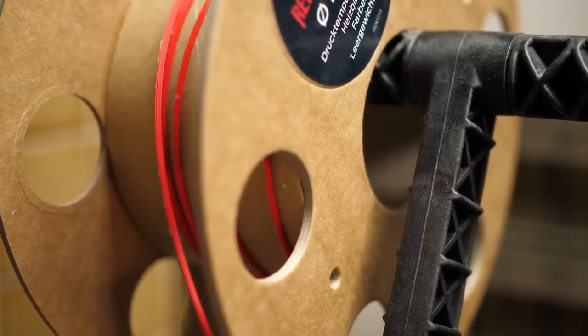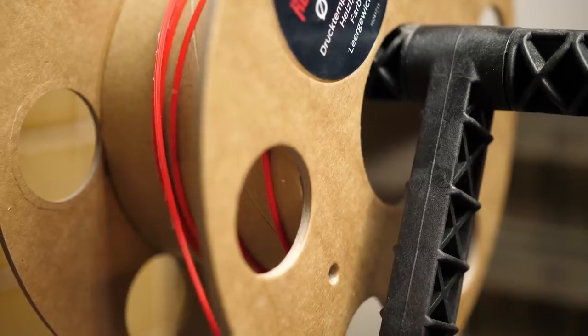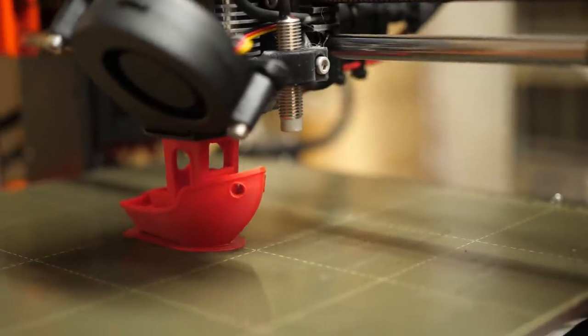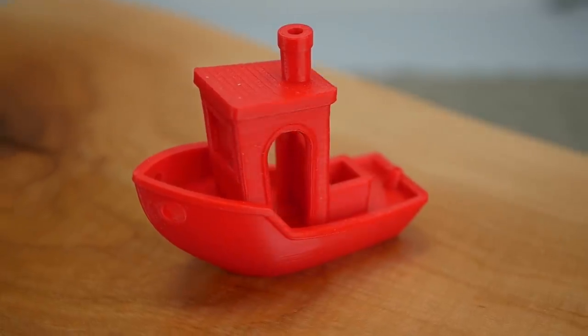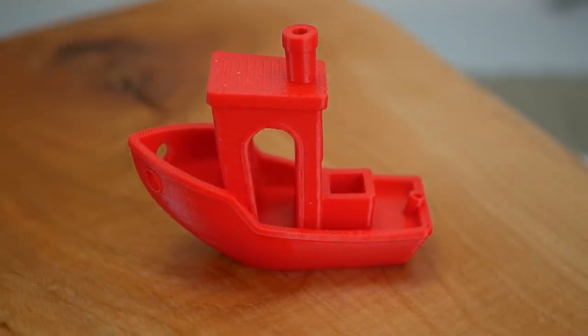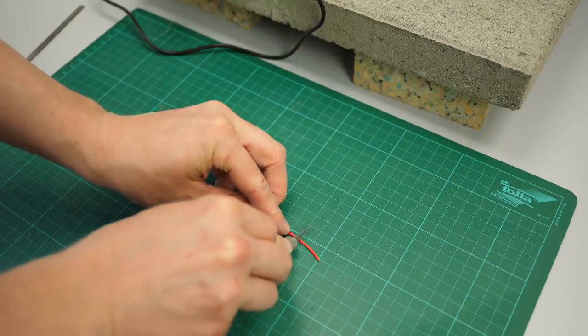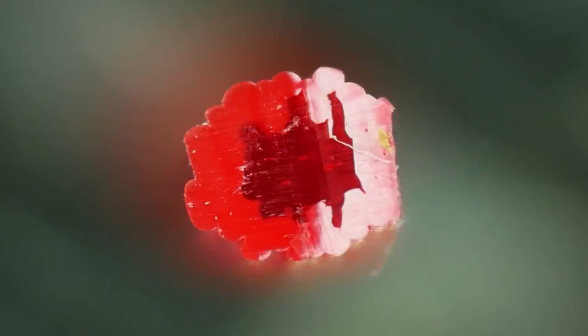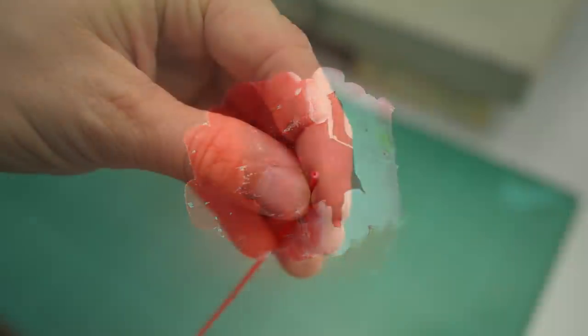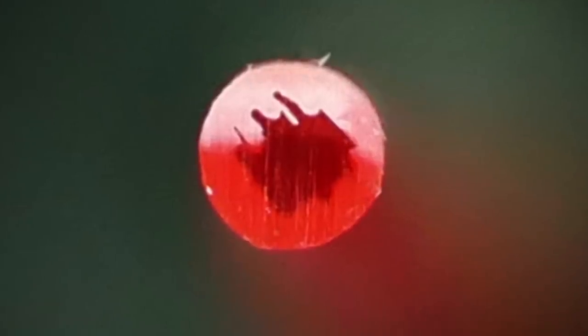I didn't find anything in the paper in regards to printing temperature for the dual material filament. I chose an in-between value of the materials and set the nozzle to 260 degrees Celsius. The print results were really stunning, especially since it's not a high-precision filament. I slightly upped the extrusion factor due to the shape but otherwise, printing results looked really good with the advantage of the nice surface finish of the ABS but less overheating problems. I cut a section of the filament with an X-Acto knife to nicely show the internal structure. We can see the transparent core of the polycarbonate and the hull of ABS. Don't mind the white part, that's just from cutting the ABS. If we do the same thing, just with a piece of filament that was extruded through the nozzle, we see that the structure remains and we can still distinguish ABS and PC. So laminar flow in the nozzle is confirmed.